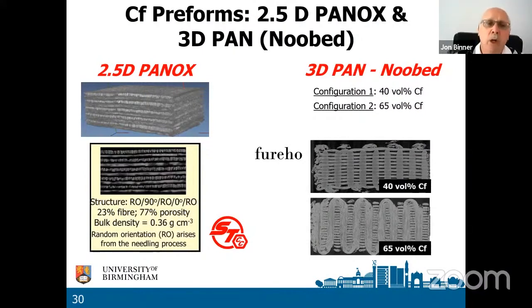So most of our work has been done on the 2.5D Panox. You can see the structure of the 2.5D. So 23% fiber, 77% porosity when we start. The bulk density is about 0.36 grams per centimeter cubed. And what you do is they're stacked in a 90-0 layer, and then you get this random orientation which arises from the needling process as you pull the fibers from one layer into the one above.